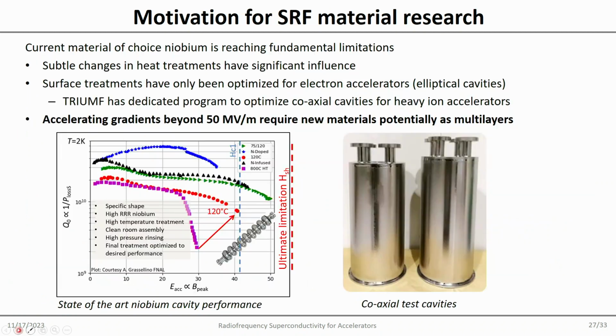The interesting thing is really that with surface engineering, just by baking it, you have a huge effect. So if you have a good cavity, you have done everything right for that one. Everything is clean, no field emission, good thing. And then you just bake it at 120 degrees for 48 hours. It goes here. It's a huge difference, as you see there. This makes a huge difference.